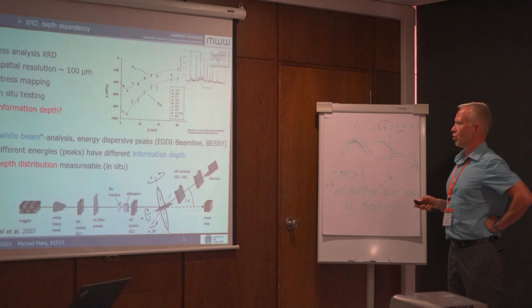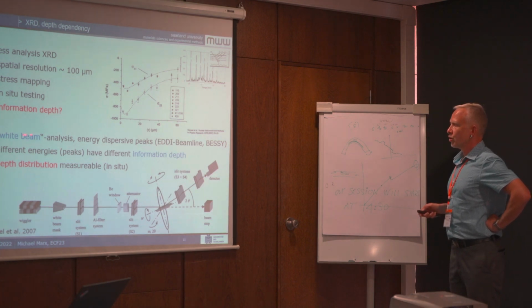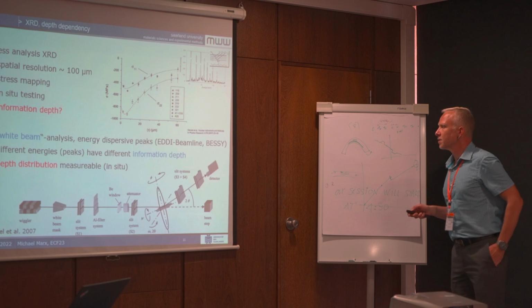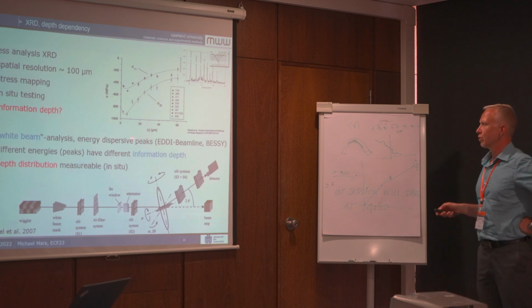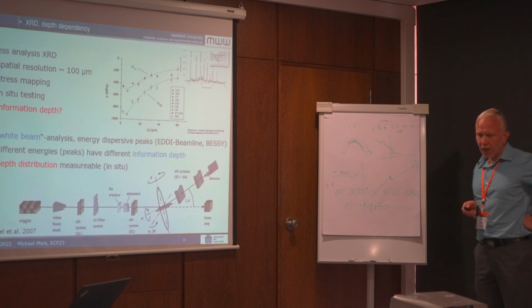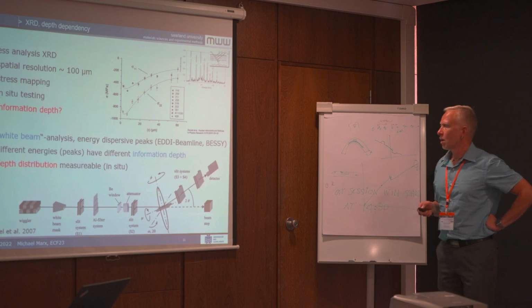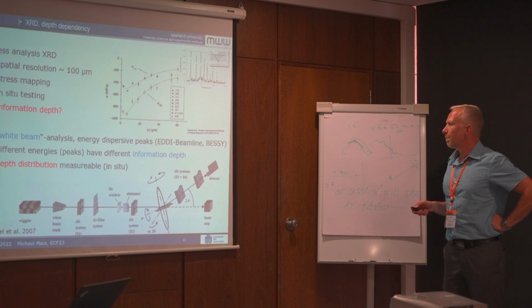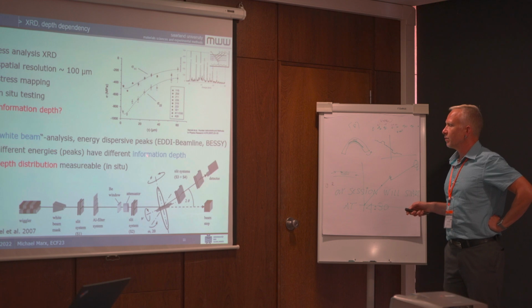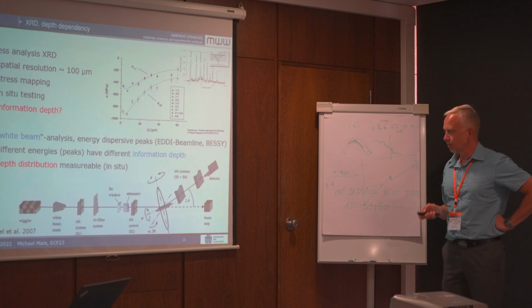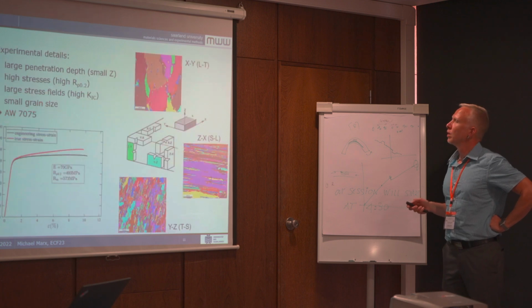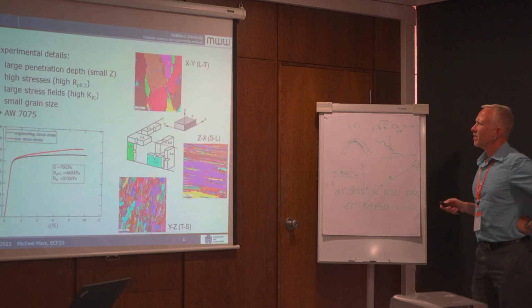So we measure this with a white beam analysis by energy dispersive peaks at the EDDI beamline at BESSY in Berlin, and these different energies have different information depth, and therefore the depth distribution can be measured in situ. Something about the experimental details.